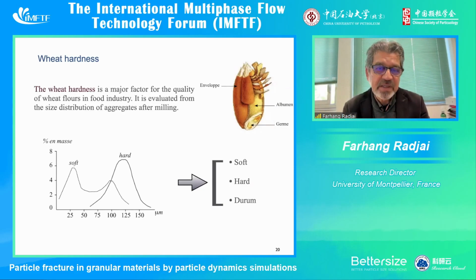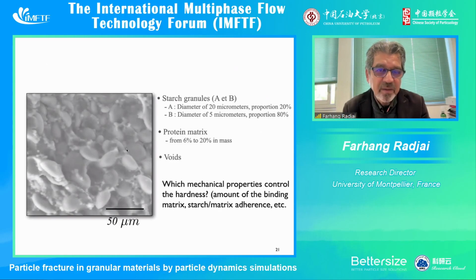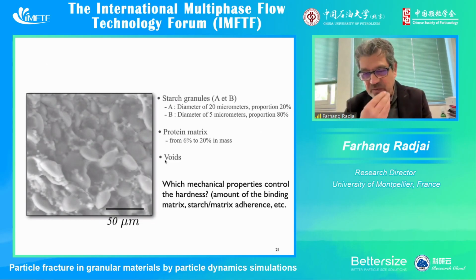So here you see a close-up on the microstructure. So it is starch granules. So it's a granular material. We have two types of starch granules of two different sizes, 20 micrometers and 5 micrometers. And the binding material is the protein matrix. So it's generally between 6 and 20%. And we have, of course, also voids inside the material. So the question that has not been well understood is which mechanical properties control the hardness of the material.